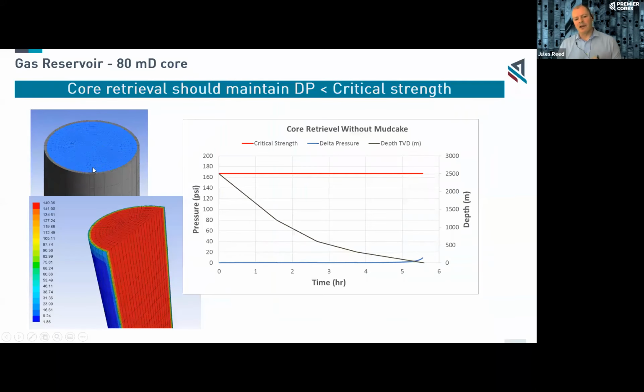So if you have some estimations or pre-knowledge of what the core properties are going to be, you can model them. And on this graph here, we have the critical strength. That is the tensile strength of that core. And then we're modeling here the reduction in pressure as we bring the core to surface. And in here, the blue is the differential pressure. That's the pressure of the gas. And as you can see, the pressure of the gas is very low compared to the tensile strength. So that's going to be no problem.